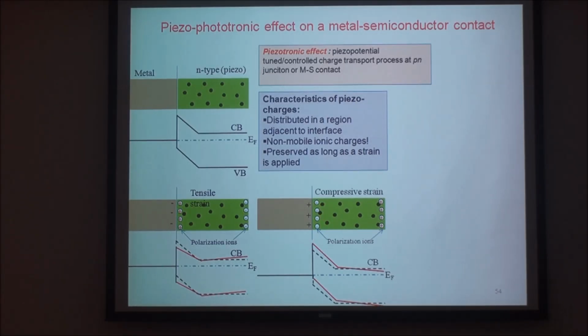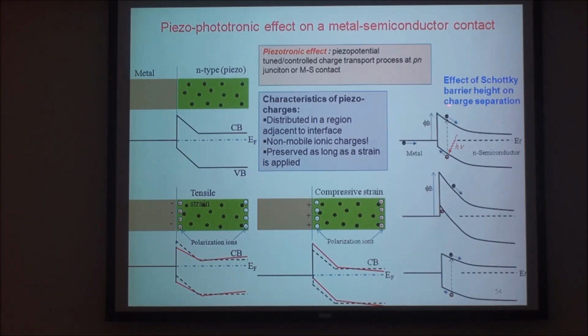What does this have to do with my device? Let's look at the band diagram here. If you use photons to excite electron-hole pairs, and you introduce negative ions at the interface, you raise the barrier height. That accelerates electron separation, but could trap the holes. So this is favorable for electron separation, but not holes. But if you use this ionic charge to lower the barrier height, it decelerates the electron separation, but could accelerate the hole separation.